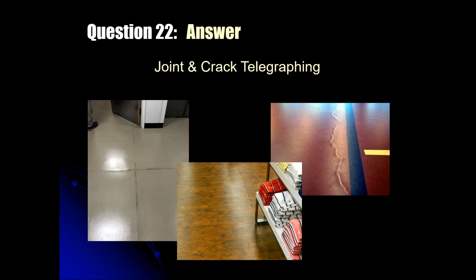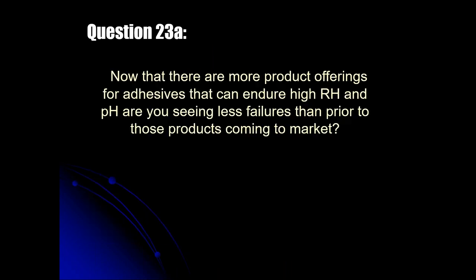And now when you come in and put your floor covering or coating over the surface, the moisture gradient that led to the warping subsides, the curling stresses subside, the slab edges go down and put whatever is in or above the joint or crack into compression. You have got to understand that there are things that need to be considered. The concrete's going to crack, but we need to have a plan ahead of time. What are we going to do about it? Because I'm going to tell you, these are going to be unbelievably expensive corrections.